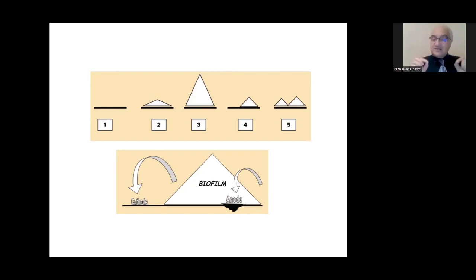Now, it is because the bacteria inside the hydrostatic testing water has corroded the weld zone in such a way that, for example, a secondary phase like iron sulfide has been produced. And this iron sulfide phase has been in contact with the weld line, therefore creating a galvanic couple. And corrosion has started from there.